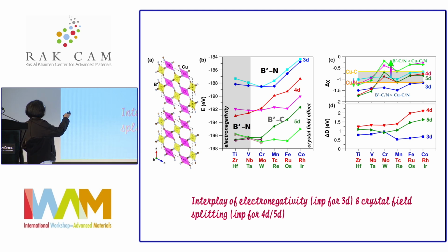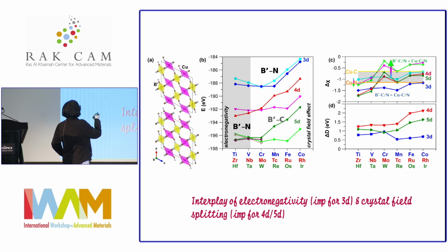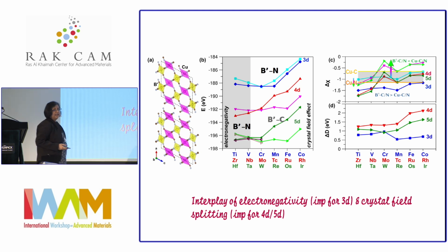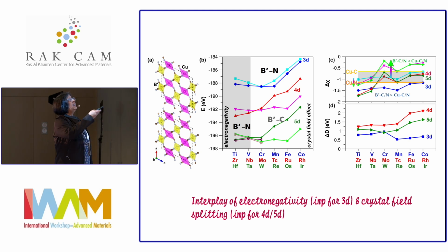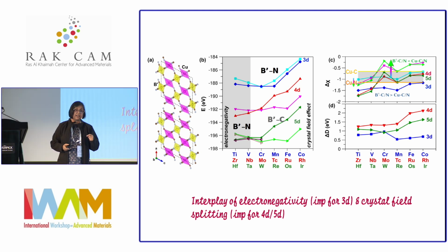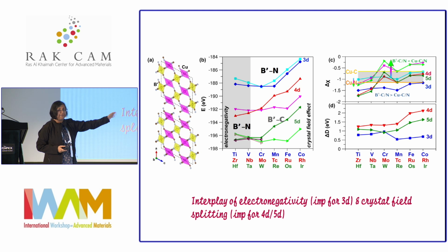For the 4D and 5D, there is an interesting thing. While for the early transition metals of the 5D and 4D, the B prime N is stabilized, but after a while, the B prime C gets stabilized. So there is some kind of an interplay. And what we found, the interplay is the following, that for the 3D series, it's basically the electronegativity difference that matters, because the electronegativity difference between the transition metal and carbon or nitrogen is much larger than that of the copper, because these are all to the left of copper.